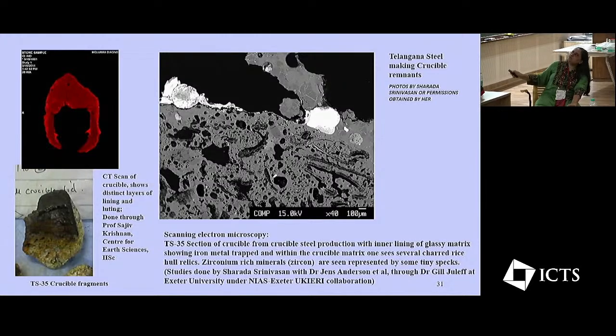It was deliberately packed with quartz and other very refractory materials so that it could withstand very high temperatures, because it had to withstand very highly reducing conditions of about 1200 to 1300 degrees centigrade. As I said, the reason that iron metallurgy developed later was because it needed very highly reducing conditions and temperatures. So that's why it was also discovered much later.